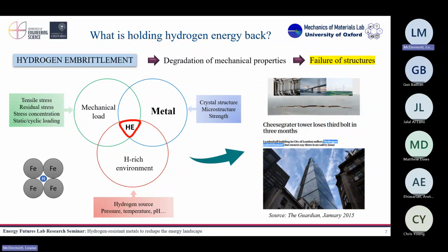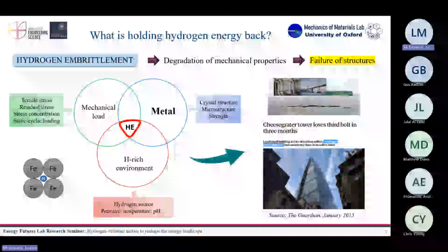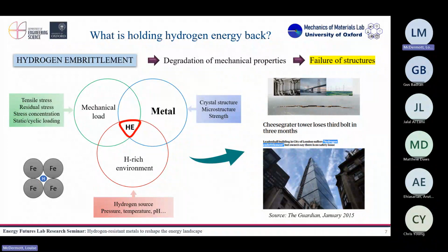We need mechanical loads. Cracking due to hydrogen embrittlement can only happen if you have a load, if you have a stress in your material. That doesn't need to be direct, it can even be a residual stress from the manufacturing process. And we need a susceptible metal. Not all metals are susceptible to hydrogen embrittlement. Usually, the higher the strength of a metal, the more susceptible it is. Carbon steels, the ones we typically see in construction, have a low yield stress, around 300, so they are not very susceptible unless we have an environment that can introduce a lot of hydrogen, or very specific conditions.